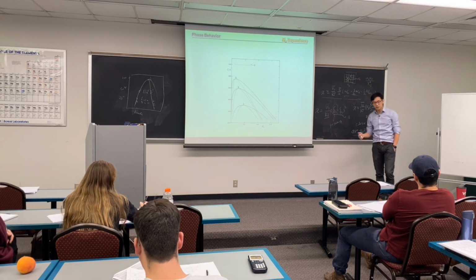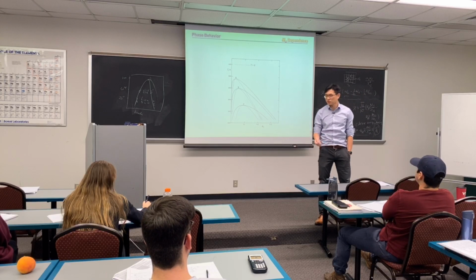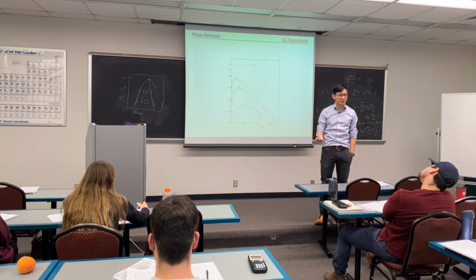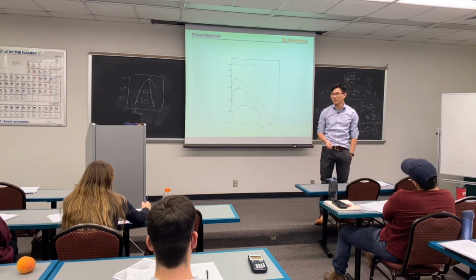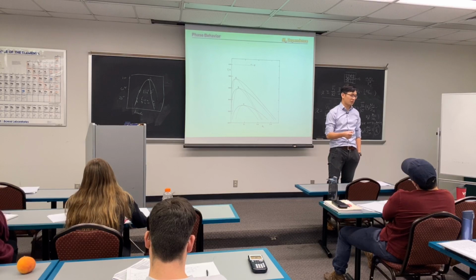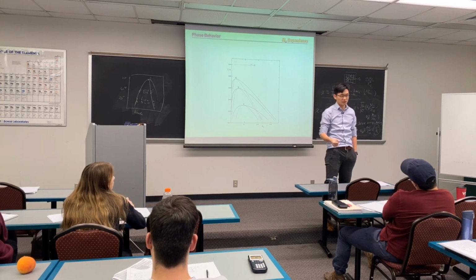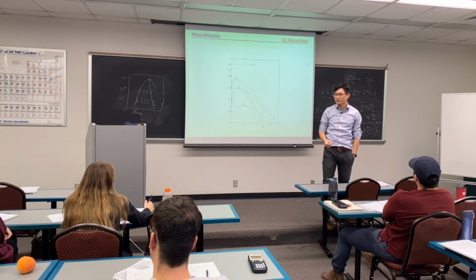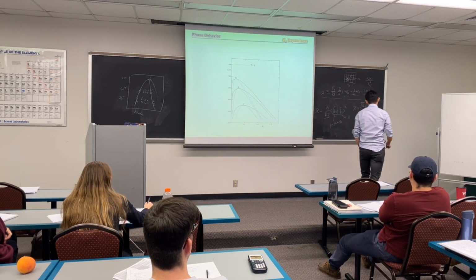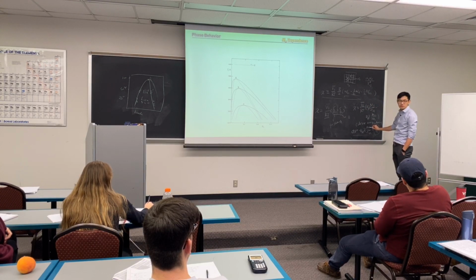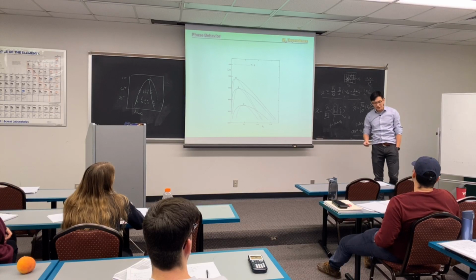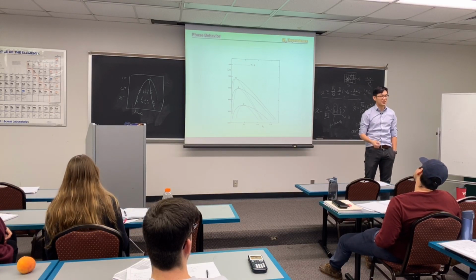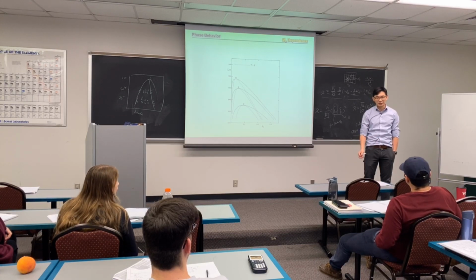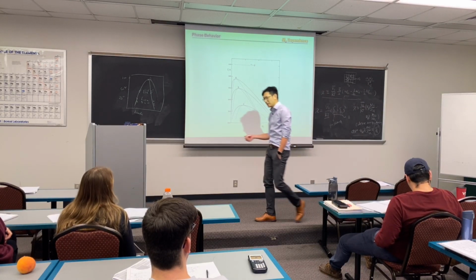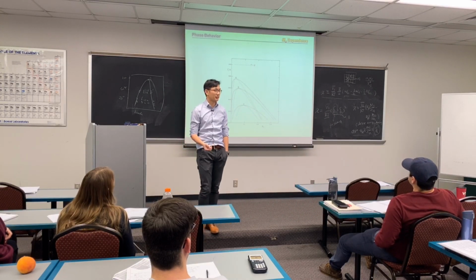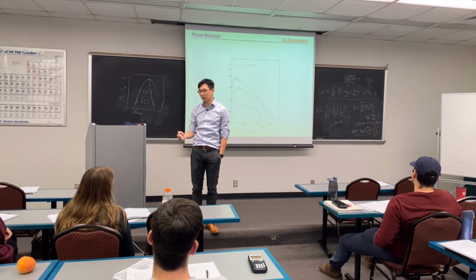Cohesive energy tells you the energy needed, let's say in toluene solvent, where you have millions of toluene molecules sitting in this room, to vaporize one toluene molecule. That would be the cohesive energy. That's very much related to W11, as you can see. Cohesive energy squared is proportional to W11. And this is a parameter that doesn't depend on a second molecule or a pair, because I only need to consider the interaction within toluene. If I remove one of the toluene molecules, you can calculate it out. This is something you can directly look up.